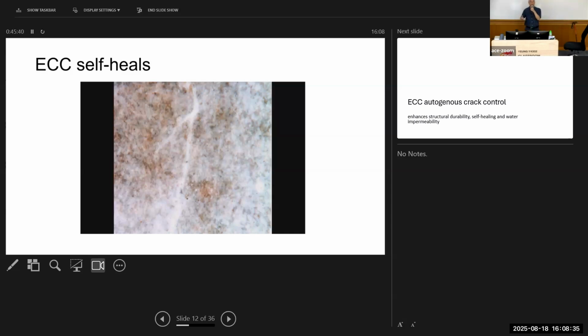But what is also happening is that it helps the specimen to not only repair superficially or visually, but it actually regains mechanical properties. You can reload this specimen and it can carry load, okay? Sometimes we have even observed situations where we have a repaired crack here. We reload this specimen and yet it creates a new crack adjacent to it, meaning that the repaired crack is stronger than the intrinsic material. So this is very important, and this happens because, or at least we think, and I hope some of you will carry out more detailed research on this,